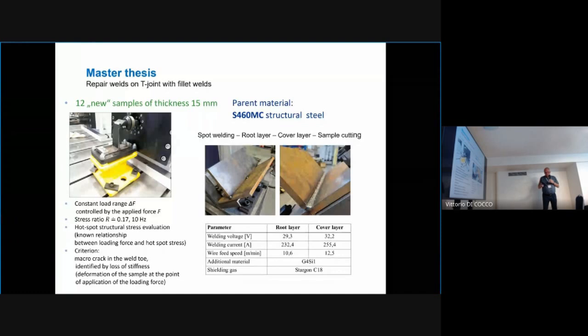And before the official program, we tested the criterion for the appearance of macro cracks, and we used as a criterion the loss of stiffness of these specimens. It means that the deformation of the loaded part was approximately 3 millimeters. At this time, we obtained the knowledge that the macro cracks will appear at the weld toe.